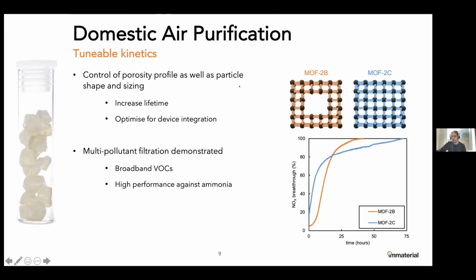And we find on a gravimetric basis, you get very much the same capacity. But what you can see here with MOF2C is we've changed the kinetics by removing the mesoporosity. So pretty much exactly what you'd expect, but certainly nice to show that experimentally. The reason why that could be particularly interesting in an air filtration application is you can imagine how this would translate to that filter operating over a much longer lifetime.